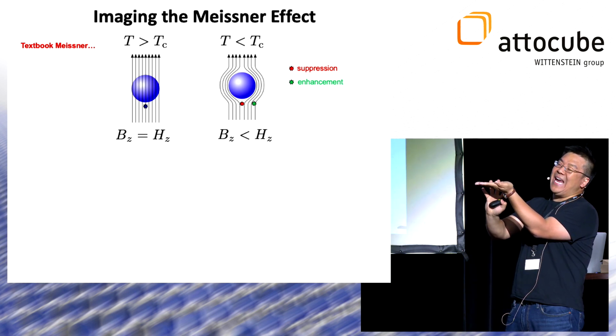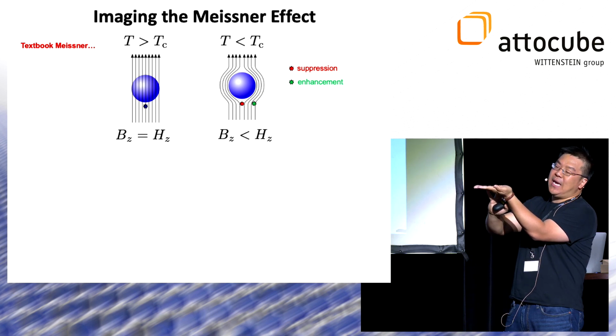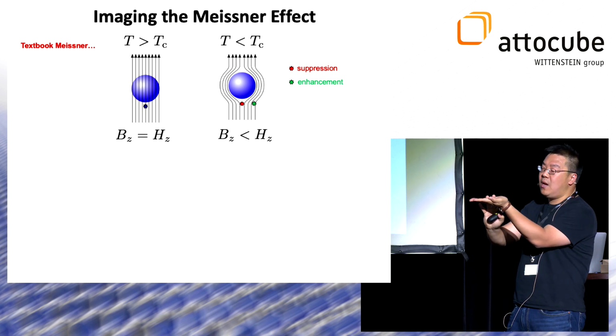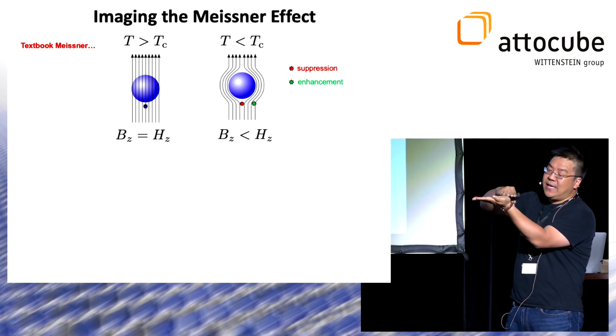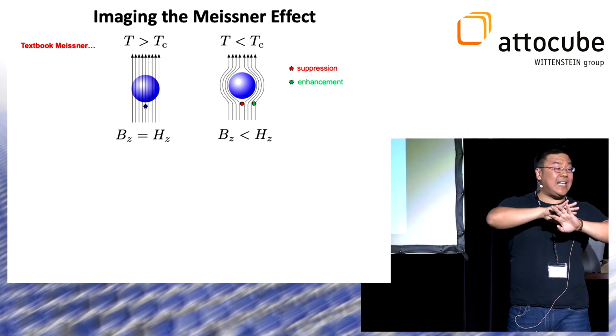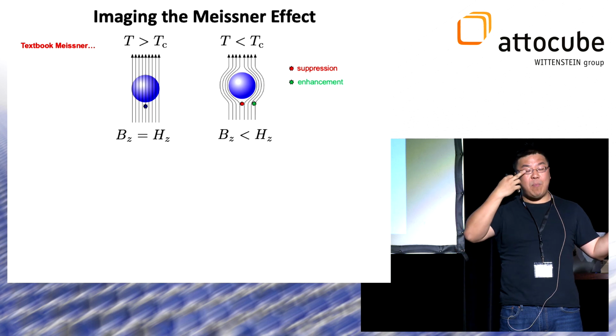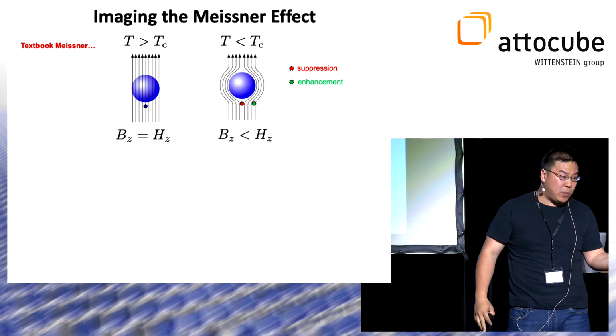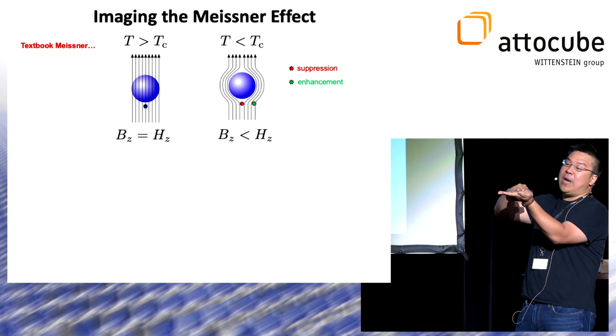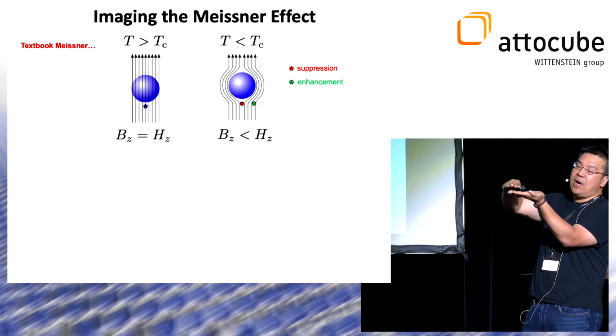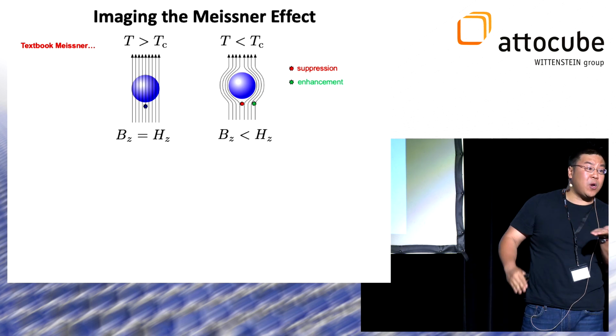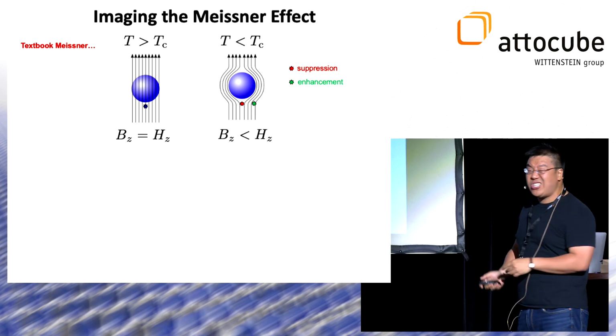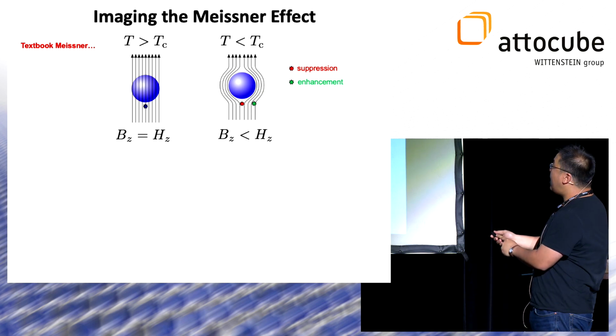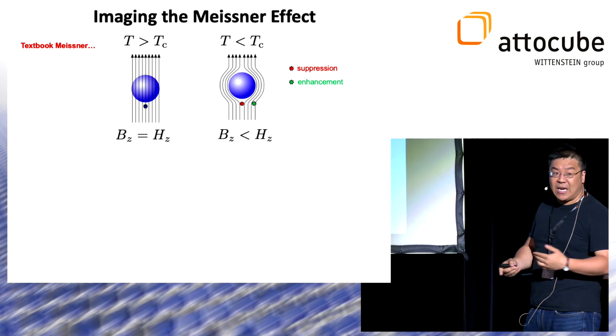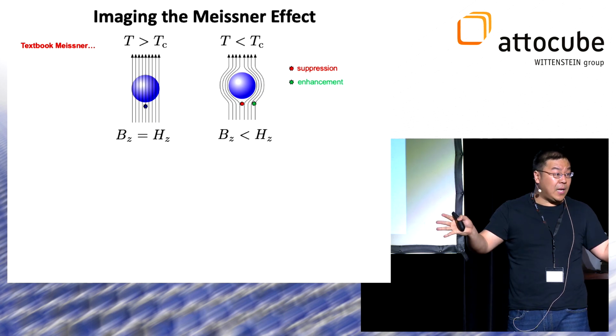So when you apply an external magnetic field, if the sample's in the normal state, in a metallic state, for example, or an insulator, you imagine that the NV centers, the sensors, should just sense exactly a spatially uniform magnetic field that's the same magnitude as what you apply. If you now have a sample in the sample chamber that undergoes a transition to superconductivity and the Meissner effect, the expectation is also kind of simple. So for sensors that are directly above the sample, you should see a reduction in the magnetic field because of this expulsion of the field lines.